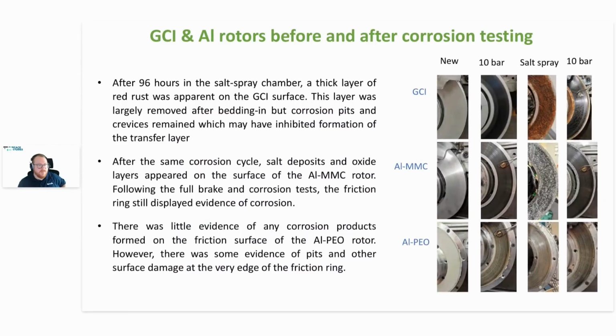This slide shows the images of the rotor surface during the various stages of the complete test cycle. Looking at the grey cast iron at the top, you can see that the nice black transfer layer has formed by the end of the uncorroded tests, looking at the 10 bar labeled there. After salt bath exposure, a thick layer of red rust has formed on the grey cast iron surface. And although the corrosion products are removed during the subsequent bedding in, scars and crevices remain on the rotor surface, which may have inhibited the formation of a stable transfer layer.